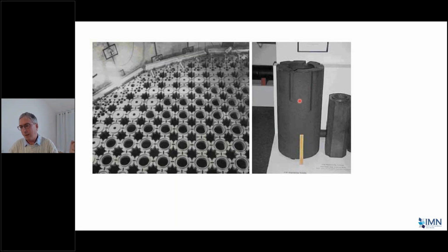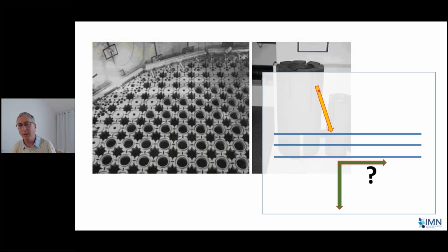And what they'll do is kick out some carbon atoms, with a very small probability, which are then traveling very fast. They then kick into other atoms and start knocking those out. Those knock into others, and you get tertiary knock-on. So all the atoms start to get this kind of scattering, all smashing into each other inside the graphite. So there's a lot of impact. It's a little bit like, on the atomic scale, you're distorting the material. You can imagine these impacts coming at an angle, and there'll be transfer of momentum. So some of the atoms will be flying out straight, but some of the momentum of that impact will be transferred to the sheet. So you're going to start sliding the sheet and pushing it along.